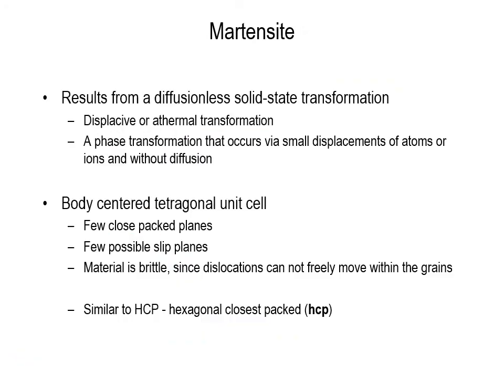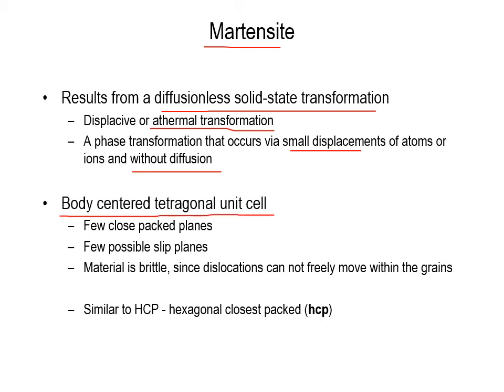If we're talking about martensite, this results from a diffusionless solid-state transformation, displacive or athermal transformation, or a phase transformation that occurs via small displacements of atoms or ions without diffusion. Now, talking about the body-centered tetragonal unit cell, BCT, there are few close packed planes, few possible slip planes, and this is brittle, since dislocations cannot freely move within the grains. This is similar to an HCP, or hexagonal close packed, structure.